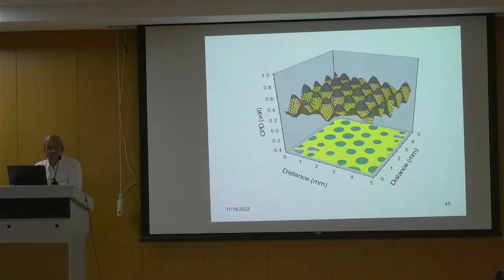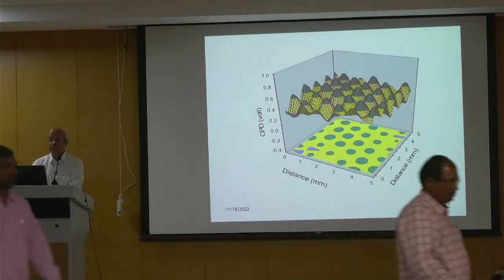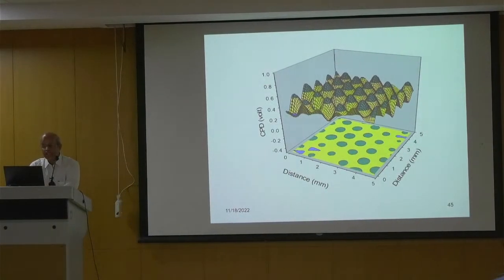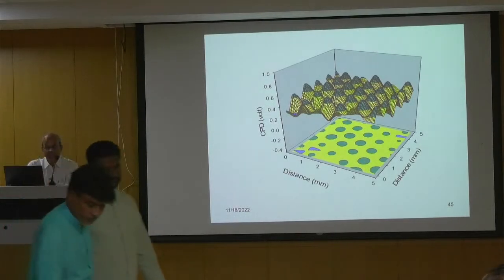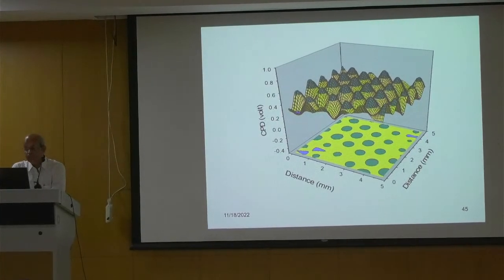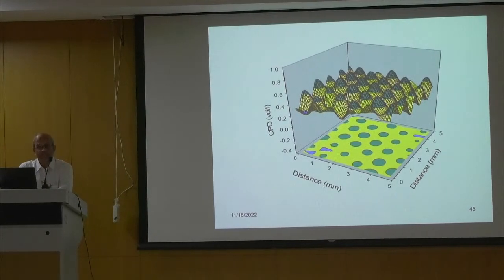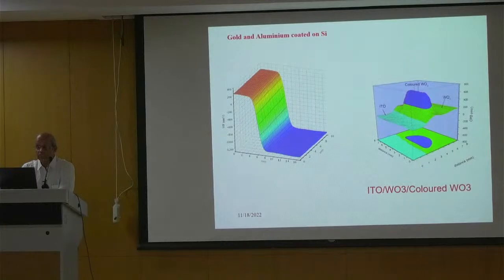In fact, we took silicon and put dots of aluminum. So wherever the dots are, we can map the Fermi level and you can see the difference. So in a scanned picture, this is the type of picture you are going to get. The z-axis is always CPD, and note that the CPD is positive or negative depending upon whether the surface is anodic or cathodic, and the scan area can be different. I have scanned 5 millimeter by 5 millimeter. You can scan 1 centimeter by 1 centimeter, whatever it is. So gold and aluminum coated on silicon show the difference.